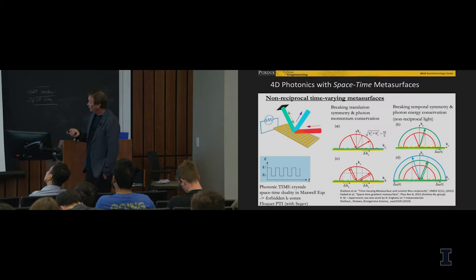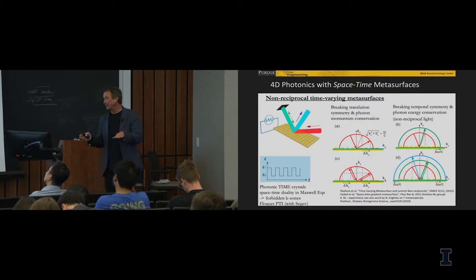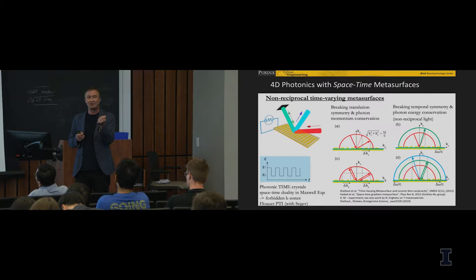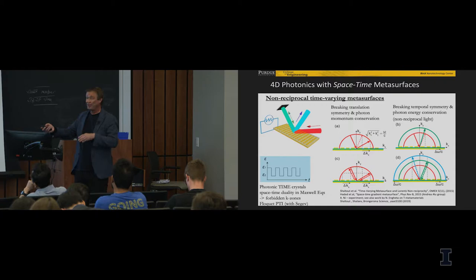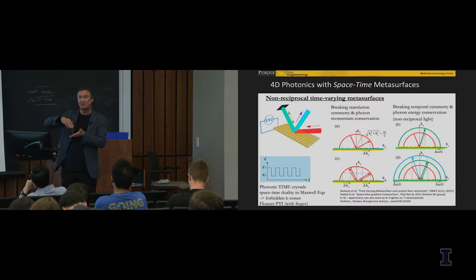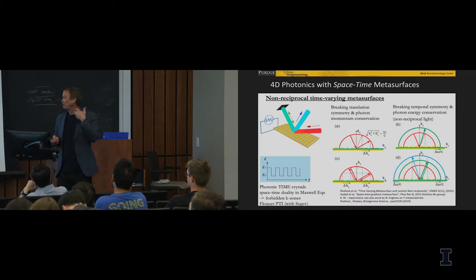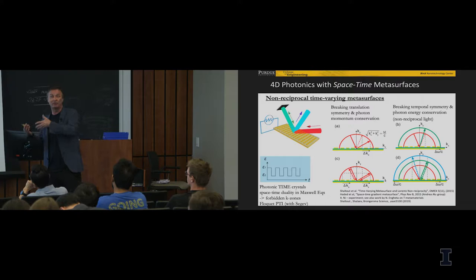Basically, you have an array of antennas. Each antenna, much smaller than the wavelength in thickness, couples to light. And when it couples to light, it shifts the phase. If the antennas are different along the interface, the phase shift will be different for different spatial positions. So in this case you have a gradient of phase along the interface. But a gradient of phase means wave vector. When you have a gradient of phase in the space domain, it's like you introduce momentum.